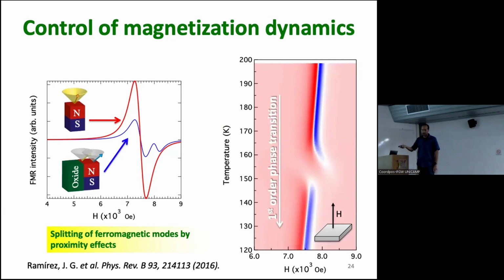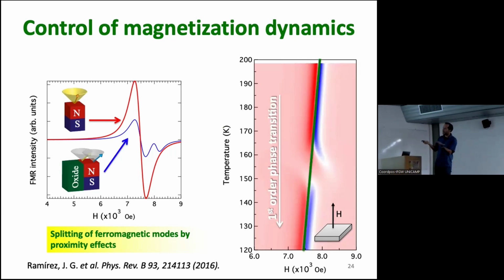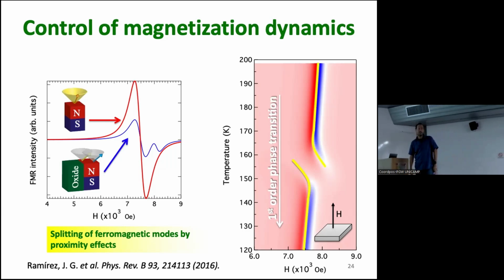If I plot all the temperatures for this particular sample, you will see that this line here that is kind of white is more or less a straight line, right? And then you have something in between, the line that actually matches exactly the nickel. But then we see something like this. So we have an anti-crossing kind of behavior. So there are magnons that are scattered between them. And this happens because the sample is highly disordered from the crystallographic point of view. But that disorder is traveling through the nickel film and is creating defects in the nickel. And the interesting part is that those defects are reversible. So I can go back, forward, and I can create those defects again every time I decide to change the temperature.